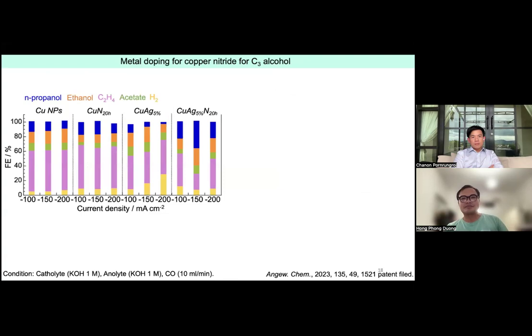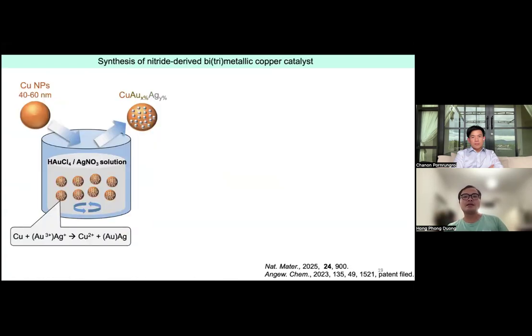And the way here is that we firstly start with the commercial nanoparticle of copper from Sigma-Aldrich, and then we perform galvanic exchange reactions. We can perform with silver or gold, or do two steps: firstly gold and then silver, just to try. You can do a lot of things here to try which combination is the best one. And then you can get things going.